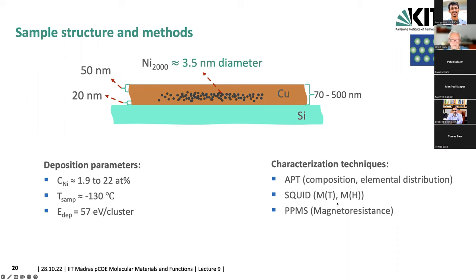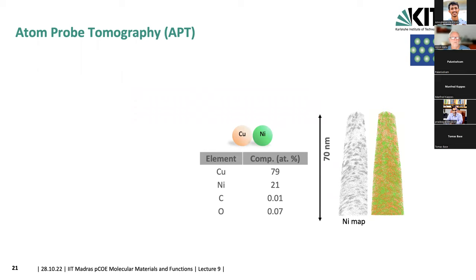So let me first show you what we found in the atom probe tomography, which is a technique where you prepare a very fine tip, and this is in nanometers up here. So the tip radius is 50 to 100 nanometers, and then you apply a very high electric field. And then you can field evaporate atoms, and they go through a time of flight mass spectrometer. So you identify what species it was. And by the position where the atoms or the ions land, you can learn where the atom came from on the sample. So you can then later trace back where the atom came from and what kind it was. So you have a 3D compositional arrangement of the atoms in your material in the tip.